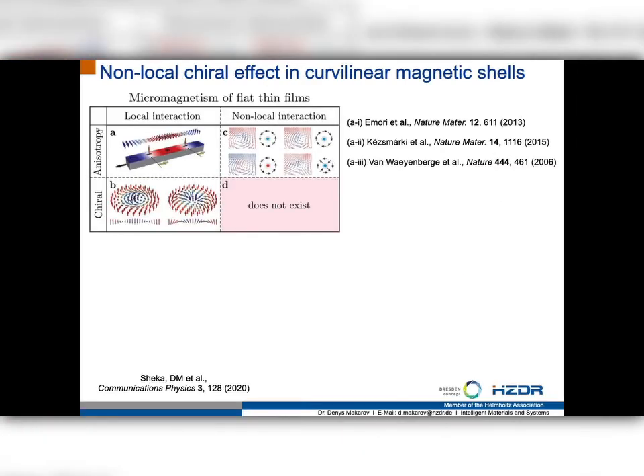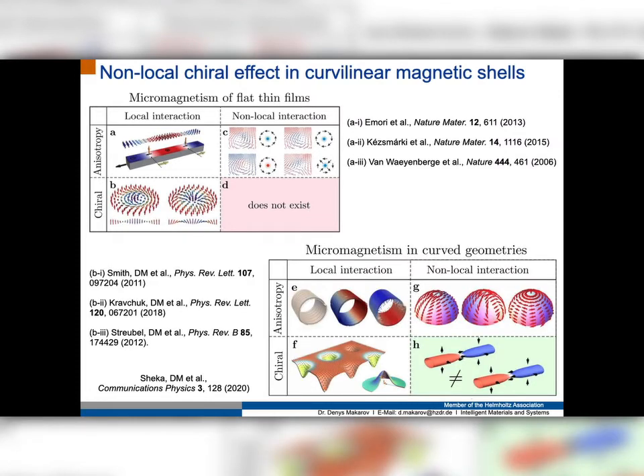I would like to come back to exactly this classical diagram where you have local and non-local interactions and what you can get out of them in terms of anisotropy and chiral interaction. What is interesting is that from local interactions you have obviously anisotropy and also Dzyaloshinskii-Moriya interactions from spin-orbit coupling, for example. Non-local interactions usually give you effects which are like anisotropy effects. What is interesting in curvilinear thin films is that these non-existing chiral effects from non-local interactions become possible to be observed.